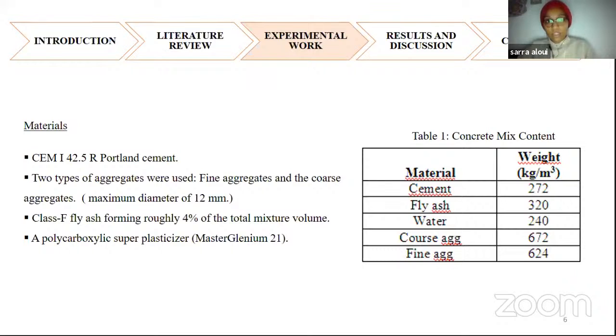Now I'm passing to the experimental work. During this project, we cast a number of beams in the laboratory where the concrete mix content had mainly Portland cement, class F fly ash, and 2 types of aggregates, in addition to a superplasticizer.